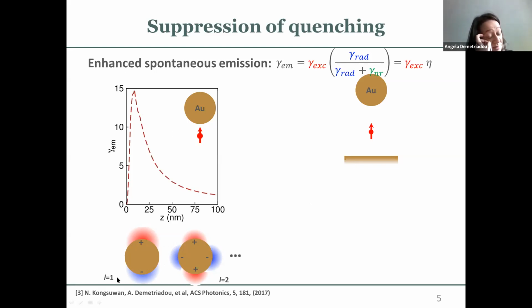And the reason that we do that is because that's the main mode that radiates to the far field. That's the one that we efficiently excite, and that's the one that we see in the far field, we measure in the far field. However, there are higher order modes supported by this system, and the field profiles are more confined on the surface of the nanoparticle. So as I move the emitter closer and closer to the surface of the nanoparticle, I couple energy to them.